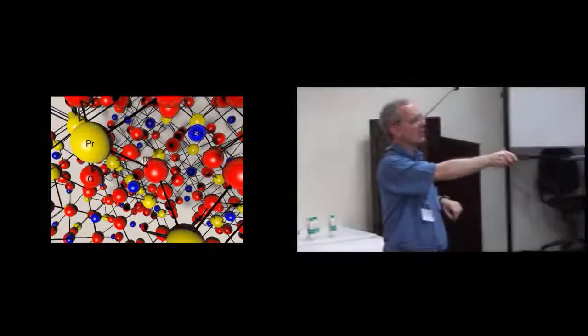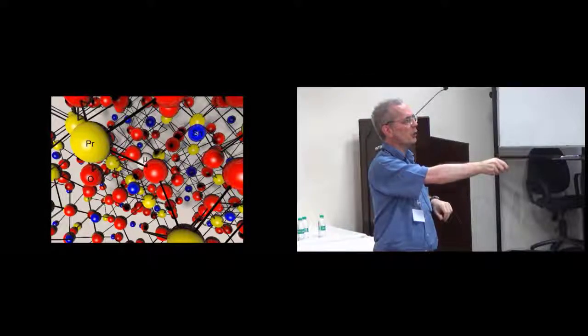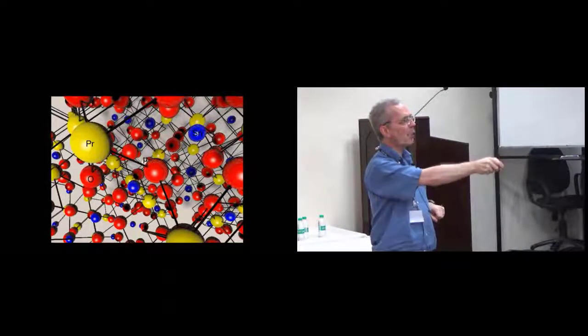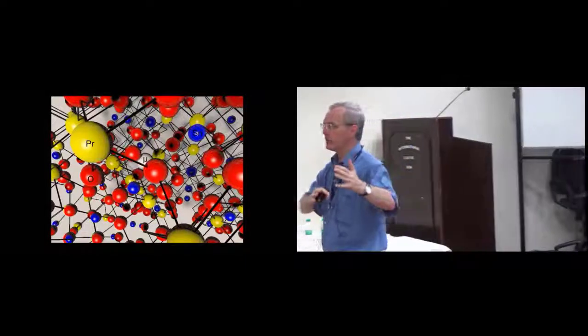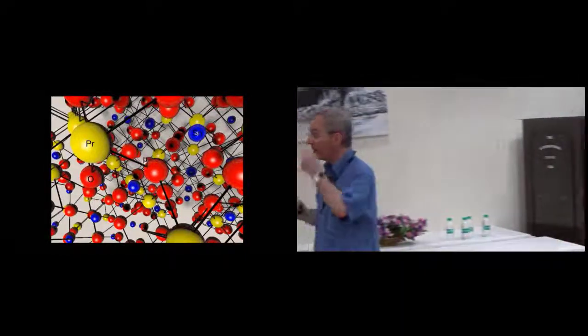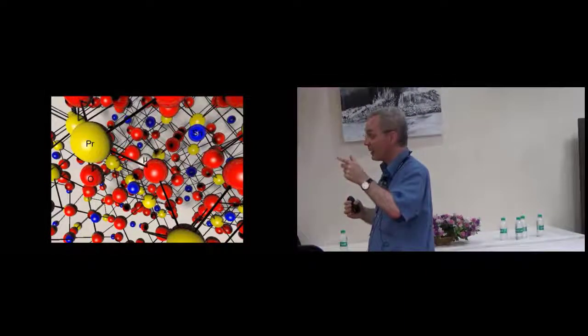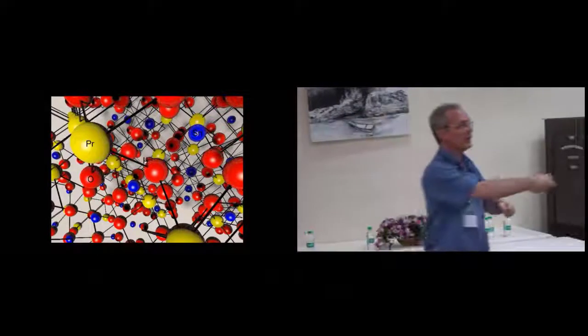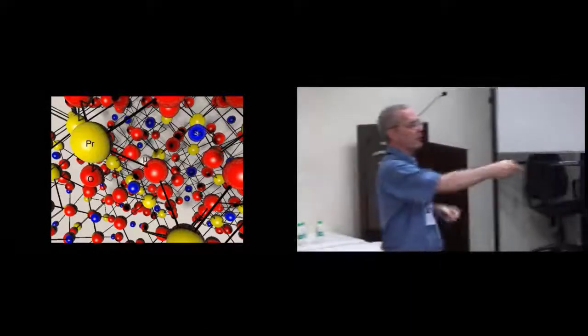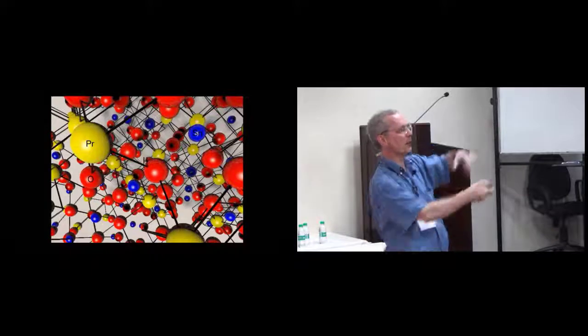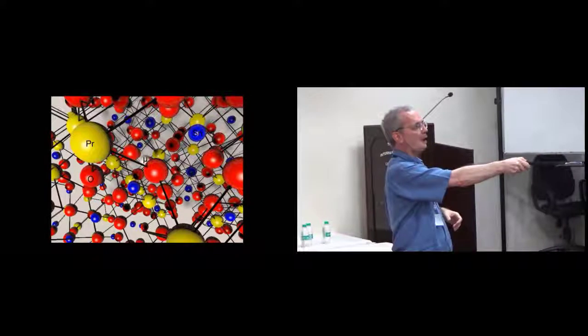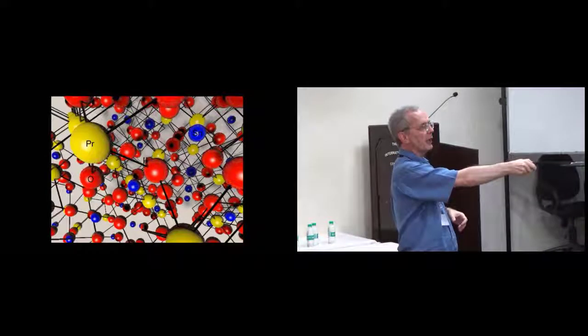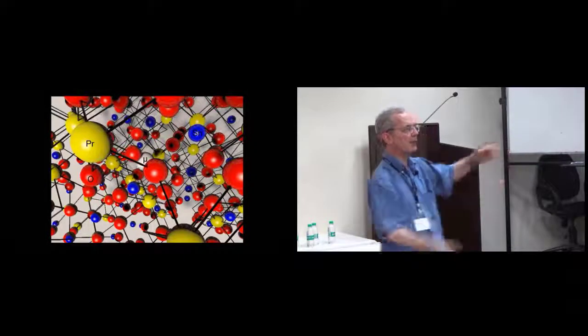The praseodymium is the yellow ion. The oxygen is red. And what I'm doing here is interpolating between no muon and muon, because the eye is very good at detecting motion. So what you can see is when you put the muon in the sample, it looks like it's growing up as a balloon, but you can see that this bond here is rotating, this oxygen is going around to meet the muon. And you can see some other ions are moving as well.